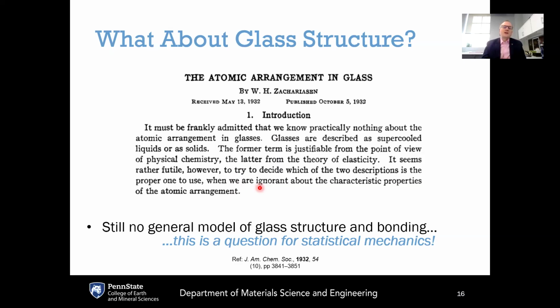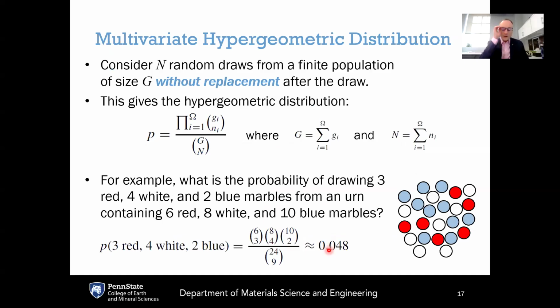Now, because we know now that the structure of glass has a large degree of disorder because of its non-crystalline nature, this means that the structure of glass is not following a perfect unit cell or any unit cell at all. And really, we've got different configurations that are possible according to different probabilities. And so this question of how to model the non-crystalline structure of glass and the bonding in glass is really a very suitable question for statistical mechanics because we don't know the structure exactly. We only know it with different probabilities. Now, what are the underlying probability distributions to describe the structure and bonding in glasses? What I'm going to show you is that the underlying probability distribution is what's called a multivariate hypergeometric distribution.